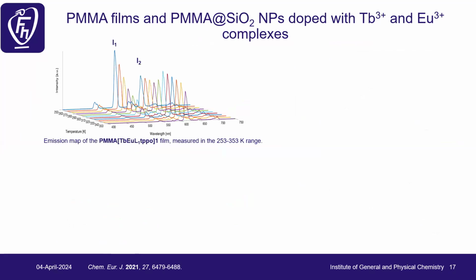So on the next slide, I will show you first terbium europium when we put it in polymeric acrylic, and here we can see a nice change of intensity of terbium at 545 and europium is more or less stable. What we want when we have ratiometric is that one is quantified by the temperature, and another one is more or less staying or getting a higher intensity. So here we can see nicely going from green yellowish to red color change. So you can see also by naked eye the change of temperature.